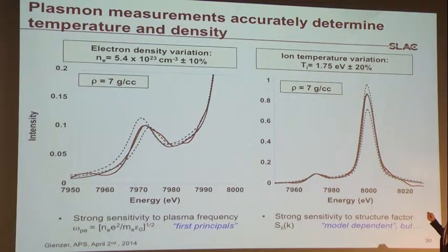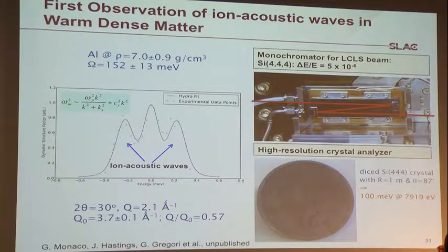The elastic scattering amplitude is also very sensitive, in this case to temperature. And in this case, you get 1.75 eV or just roughly 20,000 degrees Kelvin. So now it's a very sensitive measurement. However, it's a model-dependent measurement. There's no first principle theory yet. But there's a little but behind for those sitting on your left. You see that we believe we have a model that describes these conditions very well. And we validate this model with wave number resolved scattering. So before I go there,